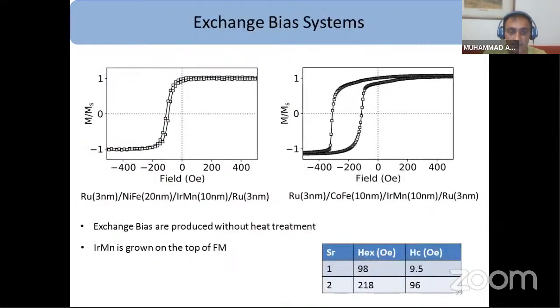Here you can see, first on the left hand side, there is a soft ferromagnet, nickel iron. Therefore it has less coercivity, and this exchange bias has potential application in sensors. And this is an exchange bias of a hard ferromagnet, cobalt iron pinned with iridium manganese. These exchange biases, furthermore, are produced without any heat treatment.